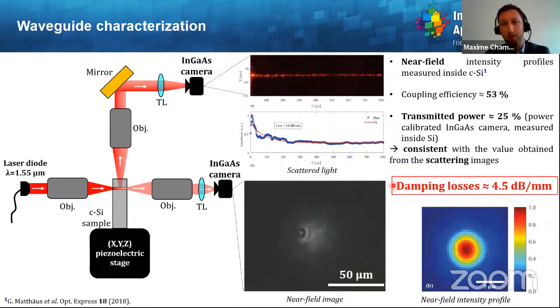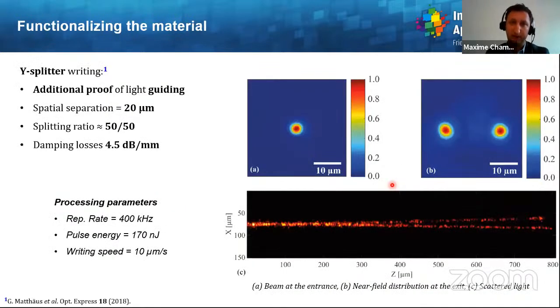And moreover, the damping losses are between 4 and 5 dB per millimeter, which is much lower than what we had before with the nanosecond pulses. Again, it was possible to demonstrate some functionalization of the material with a Y splitter, so a multiplexer, which is actually an additional proof of the light guiding. Here you can see the beam before it enters the waveguide, and here is the near field image, which corresponds to the measurements, and you can clearly see two different spots corresponding to the two different parts of the Y coupler. So the splitting ratio was 50-50, and here again the damping losses were 4 to 5 dB per millimeter.